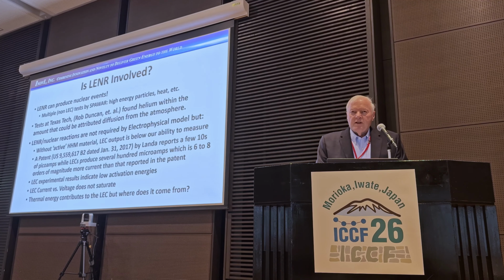Without the hydrogen host material, it's below our ability to measure. We've discovered a patent by an Israeli company that reports a few tens of picoamps with a contact electrification type device. They don't refer to any hydrogen-included metal, or even to hydrogen, but they list several different materials for work functions that they have tried. The experimental results indicate that we have low activation energies, and current and voltage do not saturate.